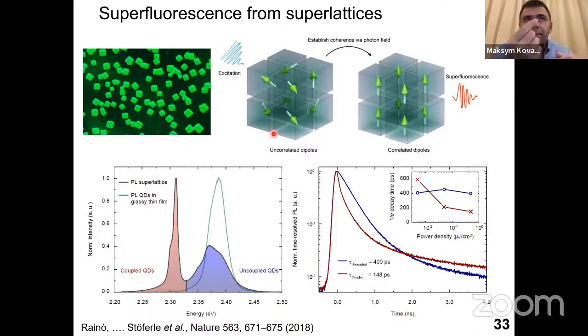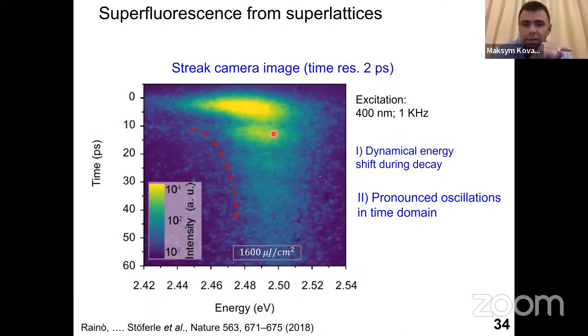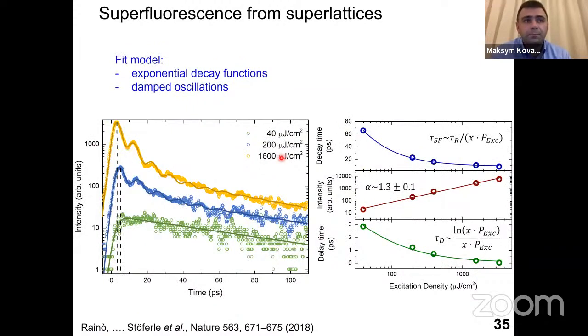So basically, as you can imagine, the higher the density of these photoexcited dots, the higher the power density for your excitation, the larger this coherent state will be, and therefore the faster the emission, and that's exactly what we see. And in addition, because it takes time to build the coherence, and then it emits, and then it circles, you have oscillations in the radiative rate, and you have a dynamic shift because as you radiate, you lose the stabilization energy from the coupling, so it goes back to the bluer energies. You nicely see these oscillations if you compare the radiative decays at different excitation densities, and you also see this linear dependence between light in and light out, which speaks for the purely radiative nature of everything that you observe.